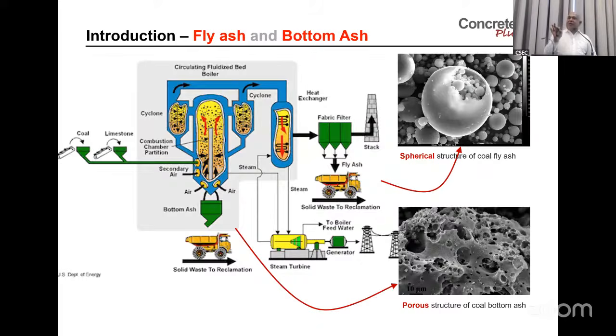So let us clarify what is bottom ash and what is fly ash, very simple. In this burning process, whatever flies out is called fly ash. It goes out with the emission, and then you collect it with filters; we call it fly ash. Obviously this is very fine and comparatively pure material. What you get at the bottom, we call bottom ash. The right side at the bottom is bottom ash. This is of very low purity, with unburned carbon, etc.